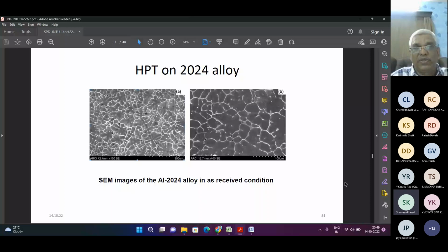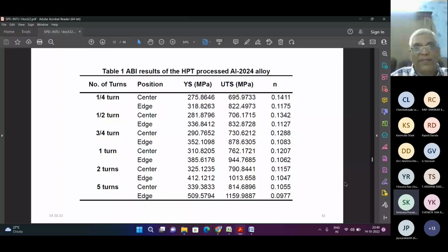Before understanding anything, you are supposed to see how the grain size reduction is taking place. Now, similarly, for this Al 2024, that is duralumin, which is extensively used for aerospace application, we have used automated ball indentation, at the center and edge, for all the turns, quarter turn to 5 turns. This is the research work we have done. You can see how YS and UTS changed. The UTS is going up to 1160 MPa with an n value of 0.09. As the value of YS increases, the n value decreases. And at the edges, you can get a UTS of 1160 MPa. These are tremendously good results, which we have published also.